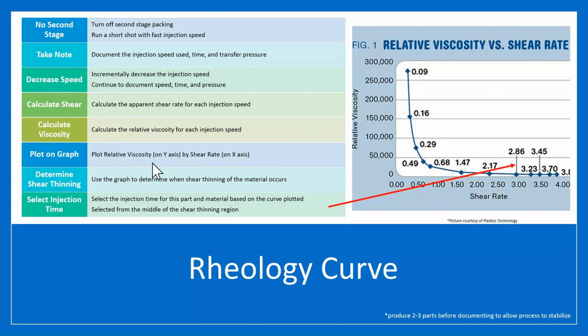We're going to plot those on a graph where the relative viscosity goes on the y-axis and the relative shear rate goes on the x-axis. What we should see then is a curve that looks similar to this, where at the lowest velocities, we are at the highest viscosity because of chain entanglement. And as we drive higher shear rates, we will drive higher degrees of shear thinning in the material, which will drive down the viscosity. So then we should be able to find a point once this is leveled out where we have repeatable velocity for our process.